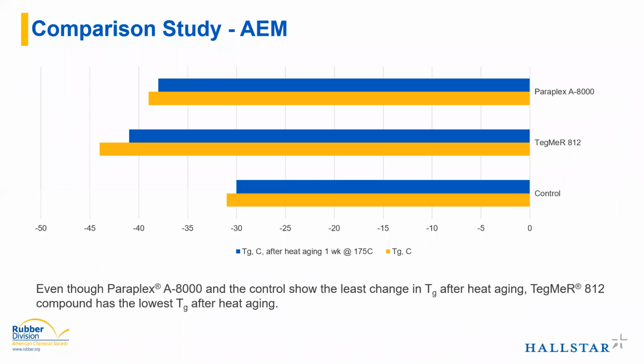But where we really saw the benefit here was in low temperature. The monomeric that we had mentioned before gave excellent initial low temperature, but also gave much better low temperature than even the initial low temp of the polymeric material. We didn't lose very much performance even after aging at a fairly high temperature in this acrylic. So it just shows how that high polarity, high molecular weight monomeric can give a good balance between the two properties.